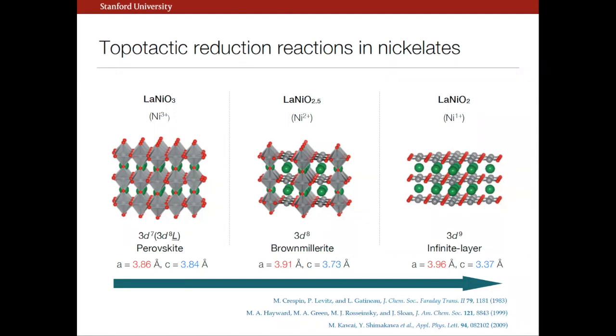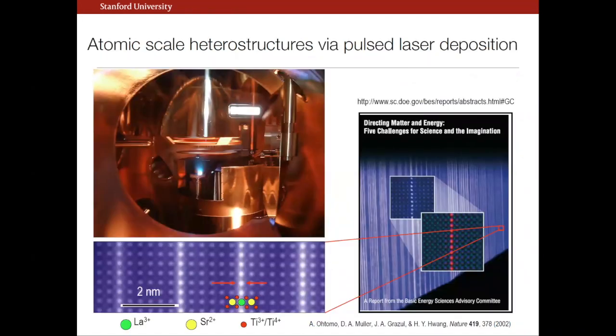Okay? There are, of course, other very important papers, but these are the three key steps that we utilize. Soft chemistry is very new to us, but what we're supposed to know how to do is make atomic scale heterostructures. In the last few decades, we've seen big advances in the ability to grow, not just by pulsed laser deposition, but molecular beam epitaxy, off-axis sputtering, fairly precise structures where you can get towards single atomic scale variations in some fairly complicated heterostructure assemblies. Another growing theme has been to use heterostructures to approach metastable states in terms of crystalline phases or interfaces that are very difficult to access in bulk.